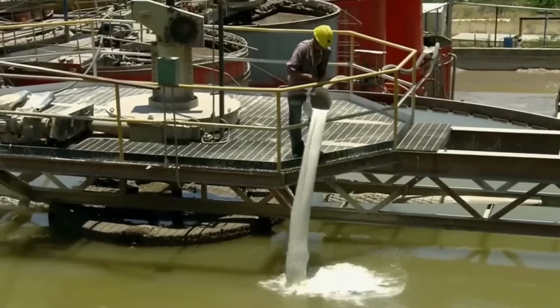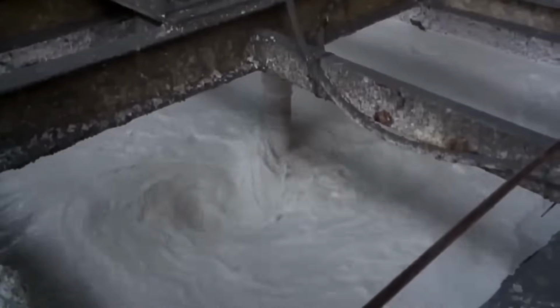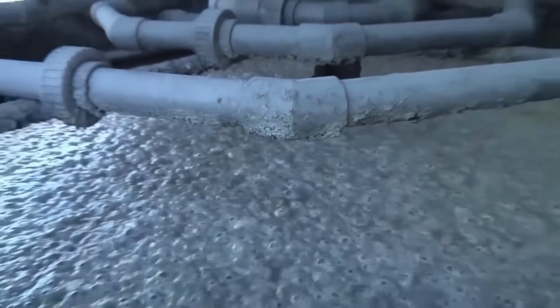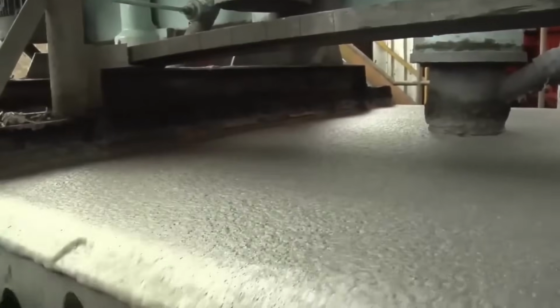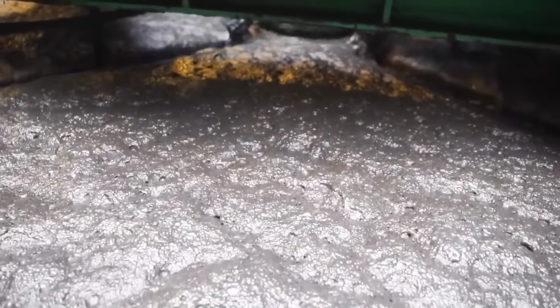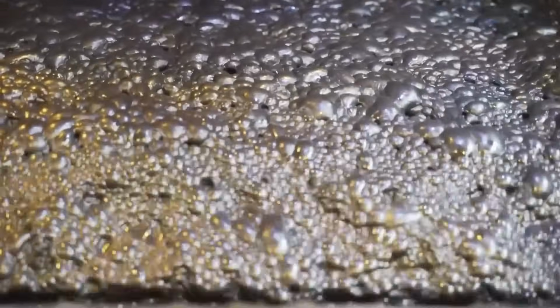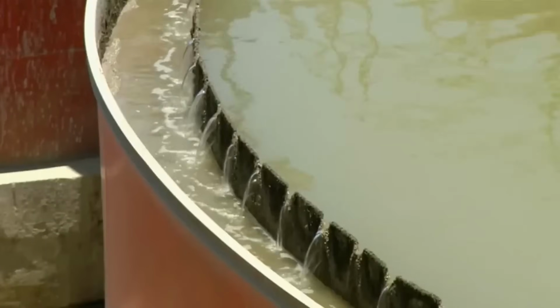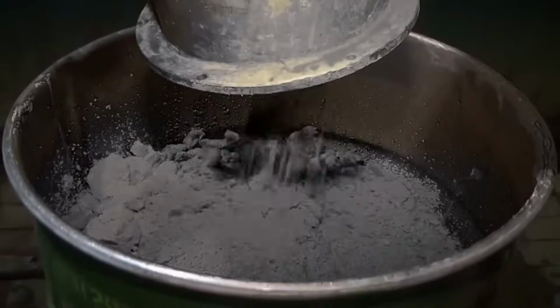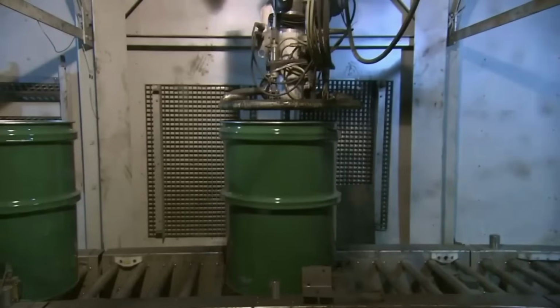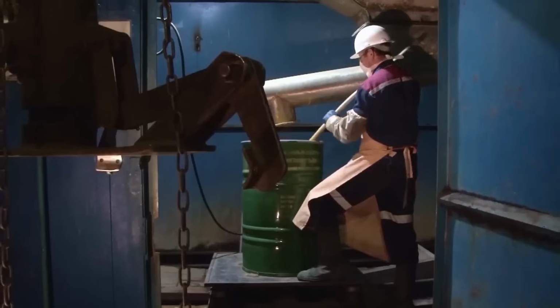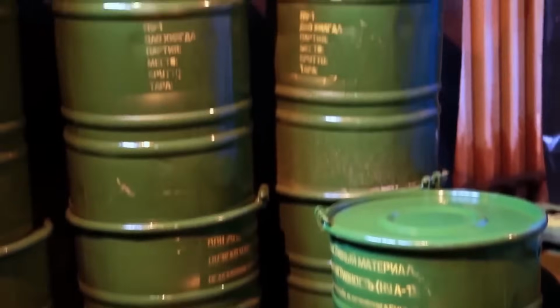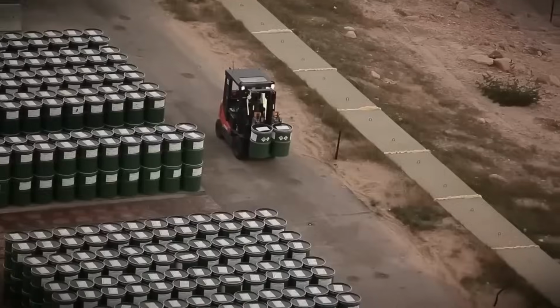The crushed ore is mixed with strong acids, like sulfuric acid, so the neodymium dissolves along with the other rare earth metals. To separate it, factories use a technique called solvent extraction, where neodymium ions get pulled out selectively through repeated cycles. After that, neodymium gets precipitated into a hydroxide, then heated until it turns into a stable oxide powder. This fine gray powder is then packed into sealed steel barrels, labeled with weight, purity, and content, and shipped out to magnet-making factories around the world.